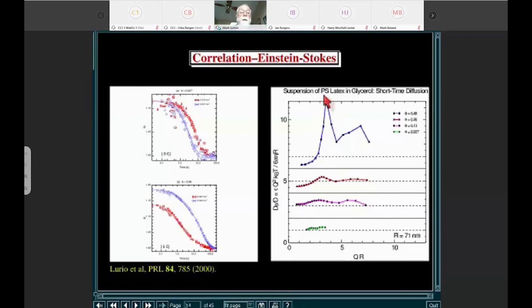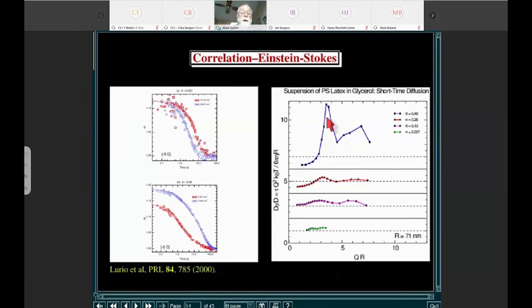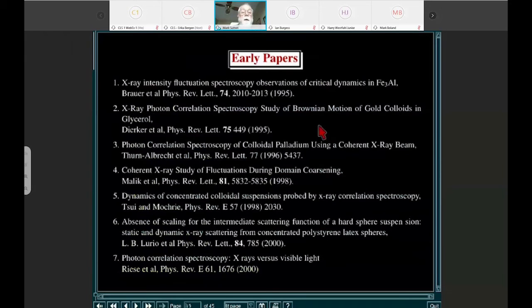And as a matter of fact, this peak is very slow. The time constant is effectively quite long at the peak of the scattering, and it's just basically measuring the fact that the particles are bumping into each other and can't diffuse around each other. So this slowdown of the diffusion constant, or the change in the time constant associated with the diffusion, is what causes the narrowing of the frequency spectrum, and that goes by the name of de Gennes narrowing. And so that gives you an idea of the type of systems we can do.